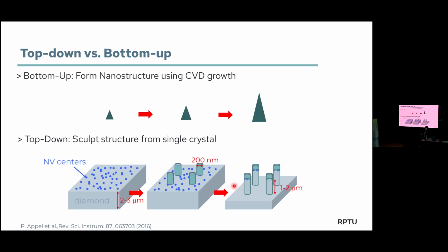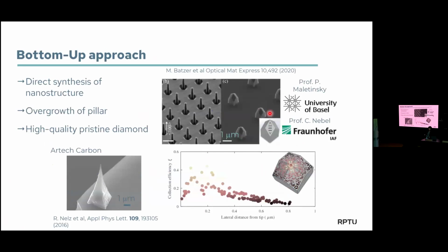And the two approaches that we have here, we can either make something that looks like a pyramid. This is done in so-called bottom-up approach. So this pyramid directly forms when the diamond is grown. And we can do a top-down where first the diamond is grown, color centers are created, and then it's processed into a pillar-like structure. And to give you examples, this is a joint work with a group of Patrick Maletinsky in Basel and Fraunhofer IAF in Freiburg. There we used such pillars, so cylindrical structures, and then we put them into the growth machine again, and we can make very nice regular pyramids with that.